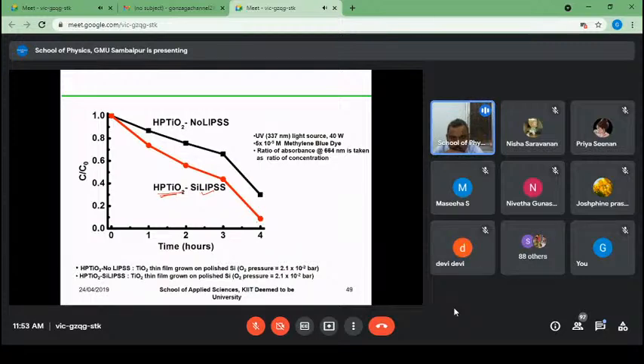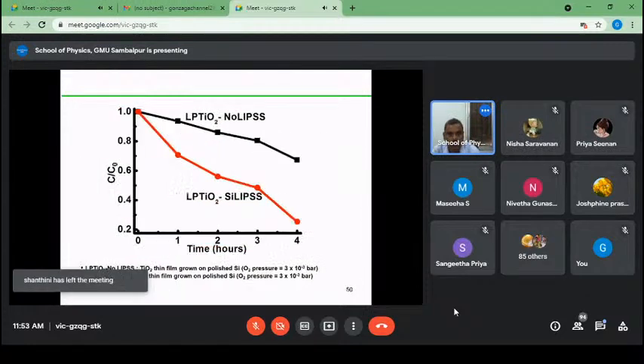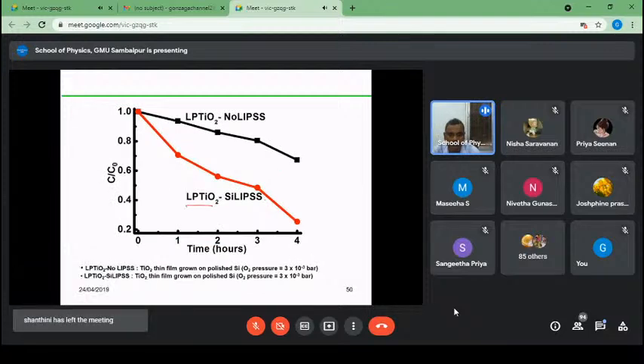You see, this is a graph showing the concentration of the dye with respect to time. The concentration of the dye was, let's say, 1 in the beginning before doing the photocatalysis. As soon as we do the photocatalysis, the dye decomposes, so the concentration reduces. Now you see here the concentration has been much lower in the presence of the LIPSS, whereas in the NoLIPSS it was not going down. So it shows much more efficient dye decomposition with these LIPSS. Similarly, with low pressure titanium dioxide, we have tested, and the results are here.